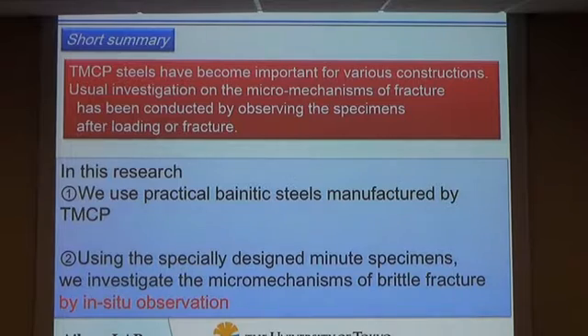So this is a short summary about the background. TMCP steels have become important for various constructions, and usual investigations on the micromechanisms of fracture have been conducted by observing the specimens after loading to fracture. So in this research, we use practical bainitic steels manufactured by TMCP, and using specially designed specimens, we investigate the micromechanisms of brittle fracture by in situ observation.